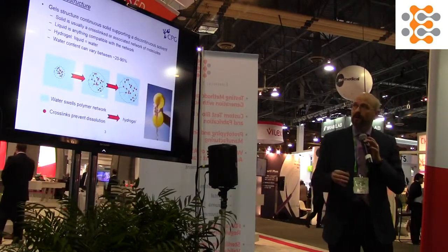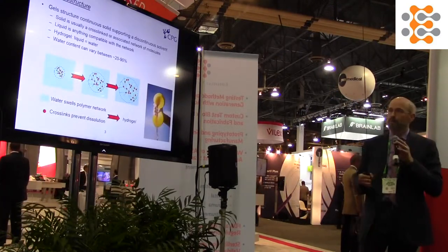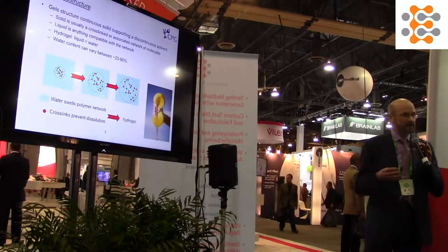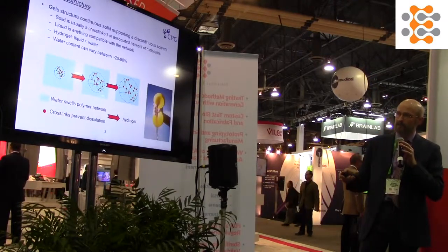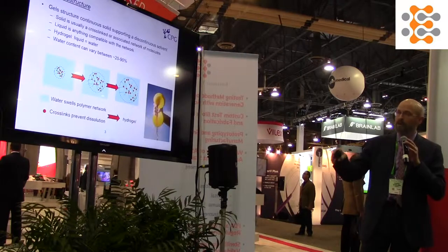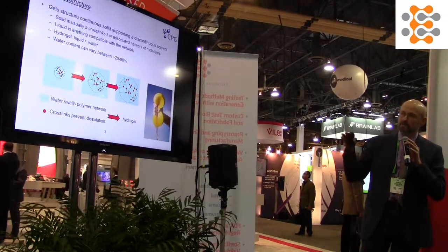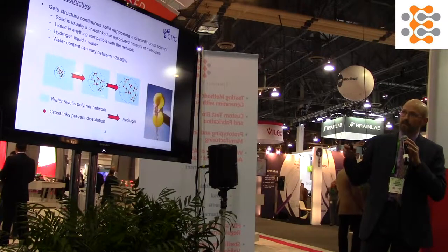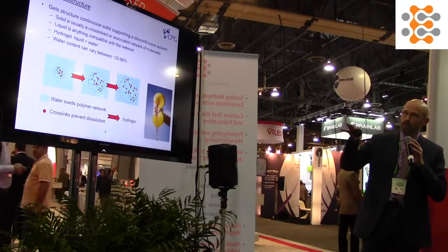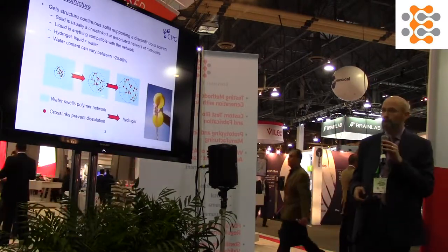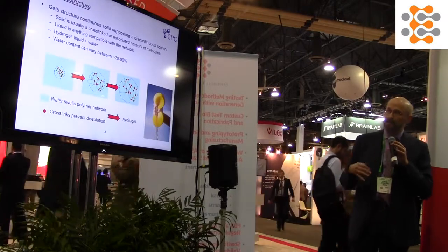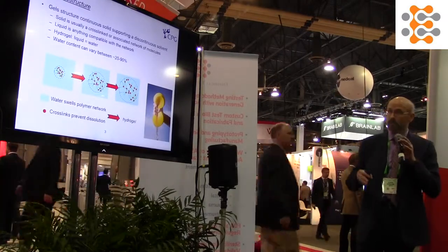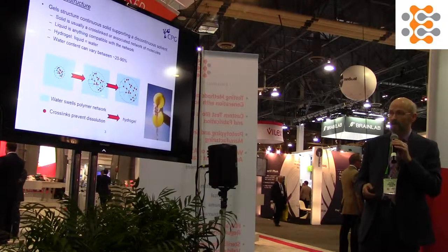The microstructure of gels is what really gives them their unique properties. It's a two-phase system composed of a solid phase, which is a network structure, and a liquid phase, which is something that wants to dissolve the material. In the case of the liquid being water, that makes it a hydrogel rather than an organogel. And the water content with typical hydrogels can vary anywhere between 20 and 90%, very high contents.